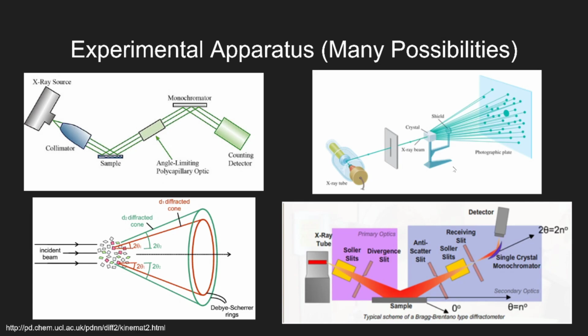And there are also some thermal effects which can come into play. As I said, you want to have elastic scattering, but you're assuming that you're elastically scattering off of a rigid crystal structure. If the crystal structure is too hot, then the atoms inside of it are jiggling around. A photon interacting with a crystal structure is like taking a picture of the crystal structure in one single moment. If the atoms are jiggling around too much, the picture that you're looking at isn't the true average picture of the crystal structure. It's a warped image where some atoms may be slightly to the left or slightly to the right of their average position. And that's brought on by thermal vibrations.